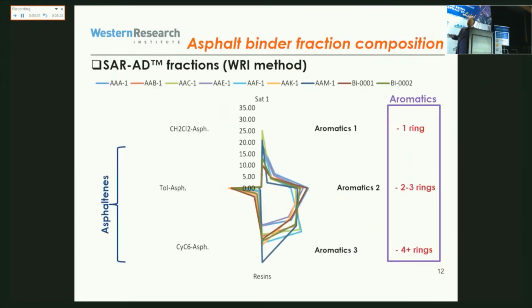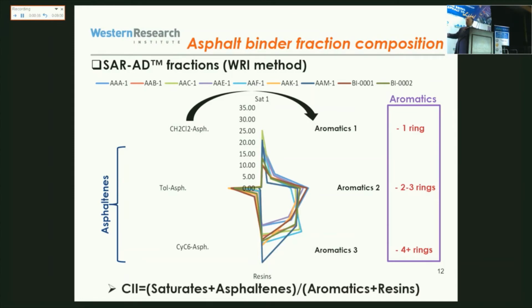So at WRI, we have developed the SAR-AD fractionation system, and I already presented that many times, but just as a reminder, from this we can get different subfractions of aromatics and also asphaltenes, and we have also the saturates and the resins. And we have done a modeling study. We know what type of molecule can be attributed to which fraction, and from that we can also measure a colloidal instability index. So we take the inverse of what Jerry did. So that's the saturates plus asphaltenes divided by aromatics plus resin. So the higher this colloidal instability index, the more unstable is the system. So this shows results for a bunch of binders, just to show that we can differentiate binders.